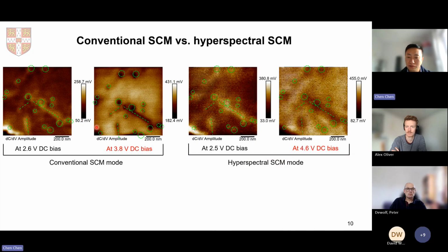We also scanned the same area using hyperspectral SCM mode. Here I plotted the local dC/dV amplitude slice from the hyperspectral SCM dataset. When we did the hyperspectral SCM measurement, there were about 128 by 128 pixels in this 1 micrometer by 1 micrometer target area. For each pixel, there's a local dC/dV curve. For each curve at each pixel, I collect the local dC/dV amplitude value at 2.5 volts. Then I can get a complete map, or a complete dC/dV amplitude slice, exactly at this DC bias value. As you can see, the features show bright contrast.